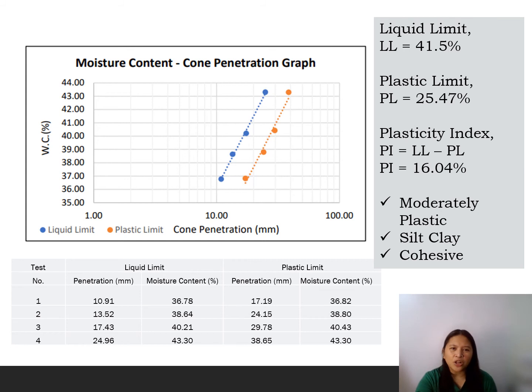So here is the result of the Atterberg limits test on the preliminary soil sample. The table shows 4 trials for the moisture content and cone depth for both liquid and plastic limit. A semi-log graph can be plotted for moisture content versus the cone penetration depth. The plot results in a straight line, and the liquid limit will be interpolated from the said plot. That is the moisture content of the soil for the cone penetration depth of 20 millimeters.